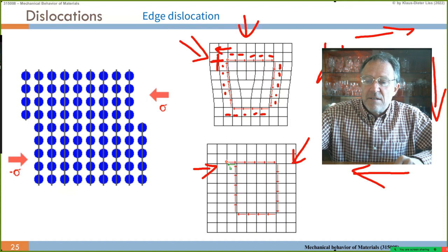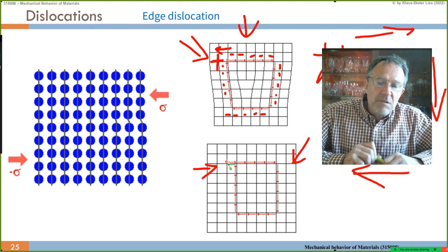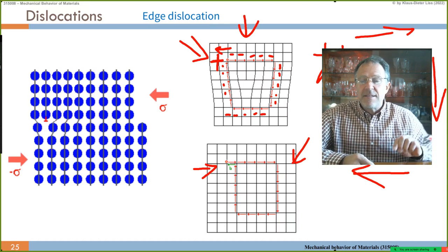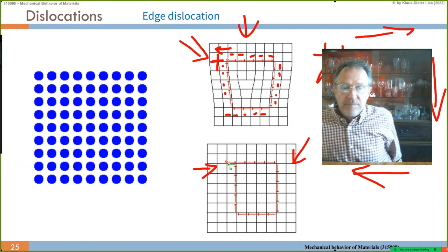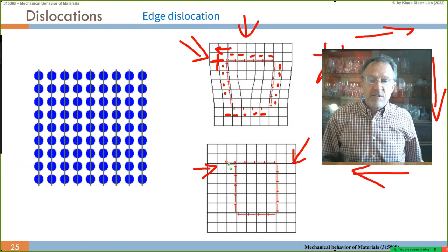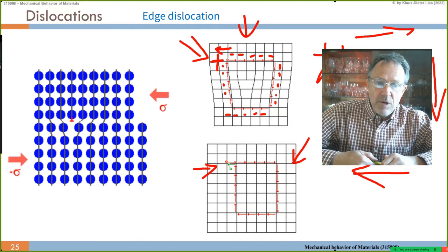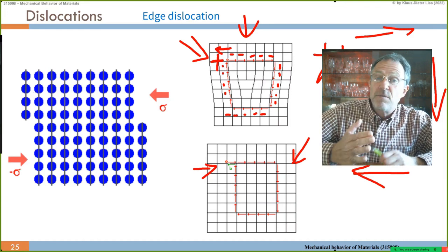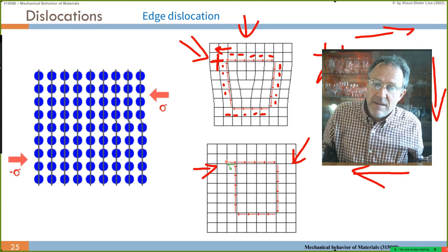And if there's a dislocation, then you end up with a different position. If there's no dislocation, just bent lattice planes, then you end up at the same position. Sometimes it's difficult to see the point of the dislocation, because we will see later on this dislocation has a width, can spread over many lattice planes.